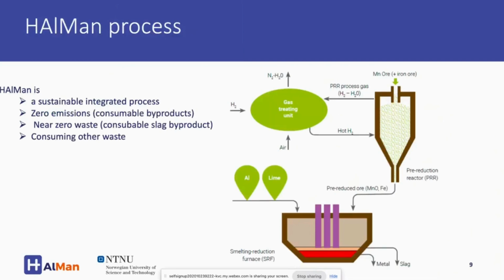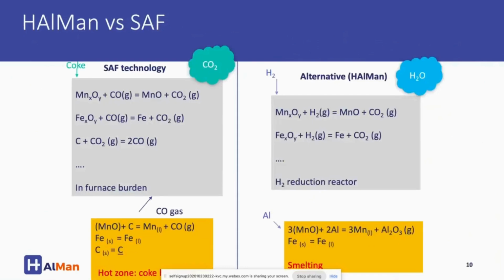And when we do pre-reduction, we get an intermediate product where we have metallic iron and manganese is in the form of MnO. Then this manganese is smelted using lime and at the same time aluminium for aluminothermic reduction, and we produce metal and slag products. So if we look at this compared to, next slide please.